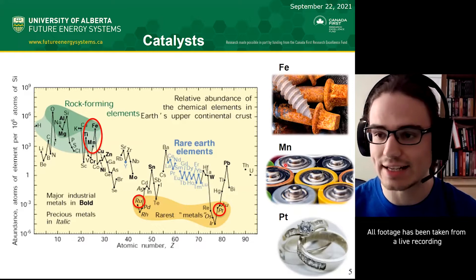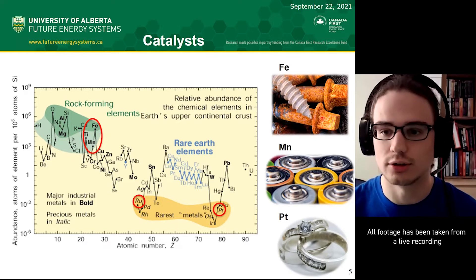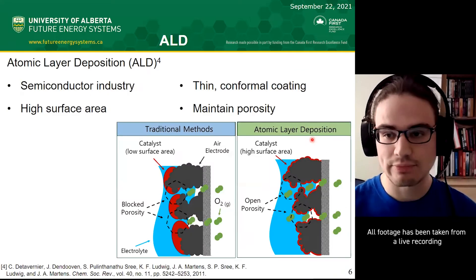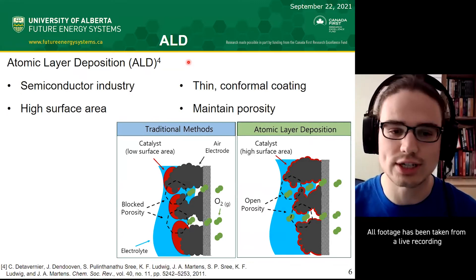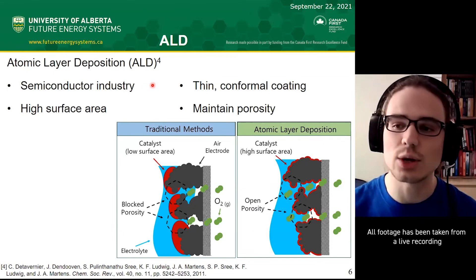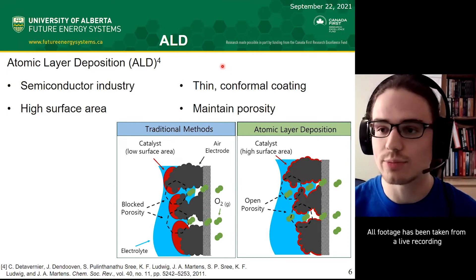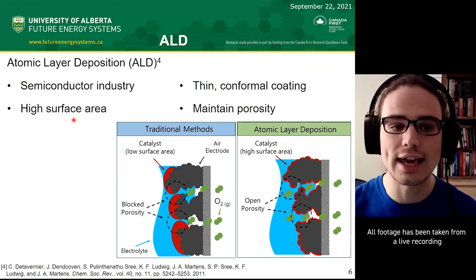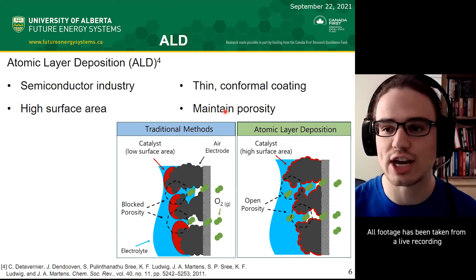Manganese oxide is actually used right now in disposable alkaline batteries as a cathode material, so we're familiar with that material. Iron oxide is just rust. So these two are pretty abundant and well-known. To create these catalysts, my research is looking at atomic layer deposition, or ALD for short, to make these catalyst layers. This technique was devised in the semiconductor industry for thin conformal coatings on microchips, but it also works for coating the air electrode in the zinc-air battery. I can get very high surface area coatings on the air electrode while maintaining the air channels and the porosity needed.